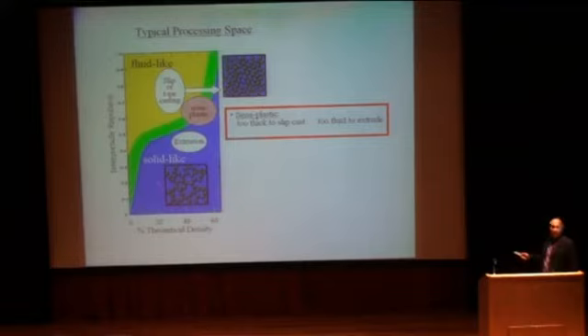Now, to turn that liquid into a solid, what you do is you take the water out of that slurry. You put it in contact with plaster, the plaster sucks the water out, and that essentially increases the density and pushes you into a solid regime. And when you're doing extrusion, you start out with a flocculated state, where the particles are all attracted to each other, and the particles actually form a network, which is now flowable and plastic, but it's still a network of particles with strained water. So now, this is a pliable material, and you can extrude it, but it's already in a solid state.